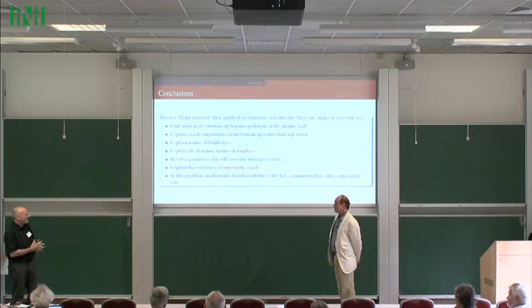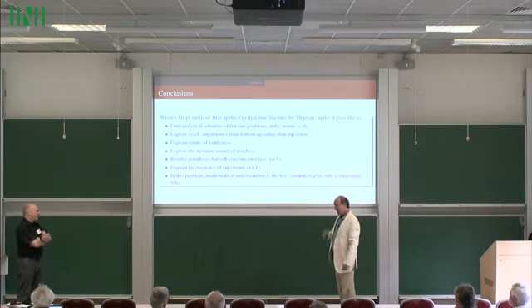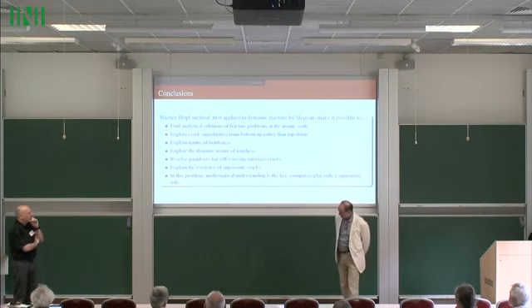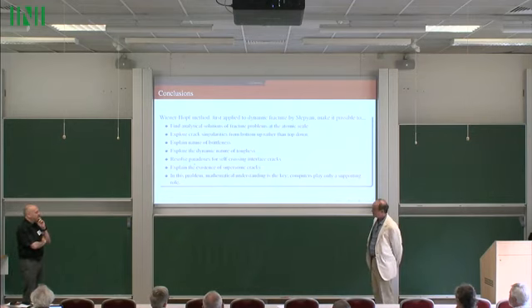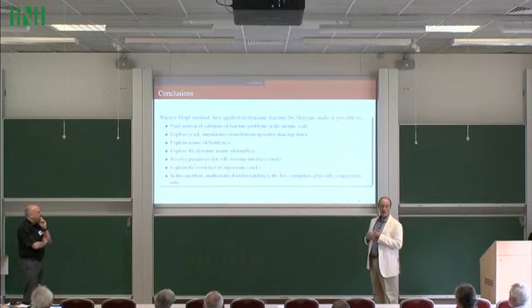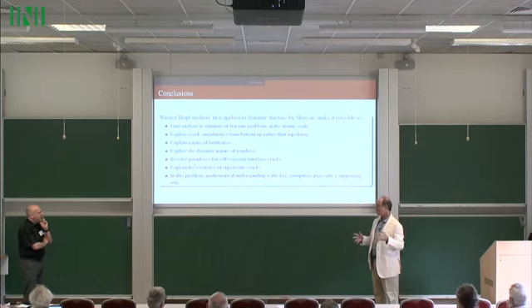So, two responses. I carried out experiments in silicon, which was the best experimental system, and there's a whole literature on that now. So there's now reasonably good agreement between theory and experiment for the specific case of silicon single crystals, which are the best single crystals there are, although they still have oxygen inclusions and of course have thermal fluctuations. Regarding the alteration of the models, I've done it numerically. I've put in all kinds of random things, and I've studied the influence of fluctuations, but neither have I done nor am I aware of any analytical work apart from some work on subcritical crack growth driven by thermal fluctuations. So I think it's entirely possible there's much more to be done along the lines you just mentioned, and I'm not aware of progress.